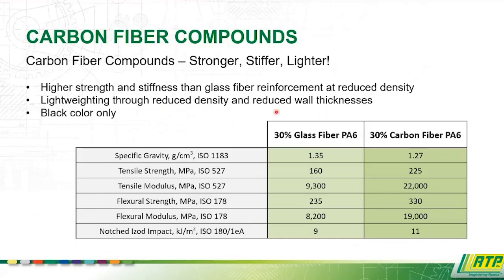Again, we'll take a quick look at some numbers. Here's a 30% glass fiber nylon 6 compared to a 30% carbon fiber nylon 6. You get that reduction in density. You get a big boost in your tensile strength, a huge boost in modulus or your stiffness, and similar impact performance. So right off the bat you can get a reduction in your gravity, but with the added properties, a lot of times you can thin wall, take some material out and reduce the weight of that part even further. Again, carbon fiber is quite a bit more expensive than glass fiber. That's why glass fiber is a workhorse. But if you're really focused on performance and weight, it's a very good reinforcement.